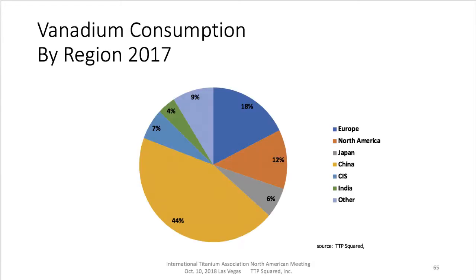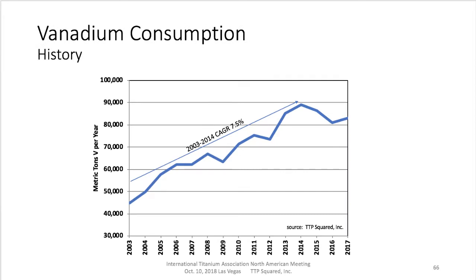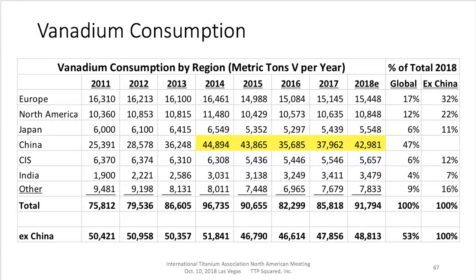On the consumption side, again, China's the major driver. 90% of the vanadium that's consumed in the world goes into the steel industry, so this picture looks a lot like steel production on a global basis. Vanadium consumption, again looking back over this 15-year period, grew at a very strong rate right up till 2014, and then we saw some significant decreases in consumption globally. If you look at the picture, this was almost entirely a Chinese phenomenon. And again, you see by 2018, the consumption has picked up.